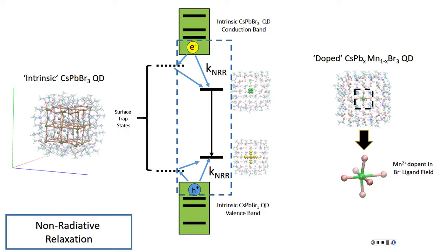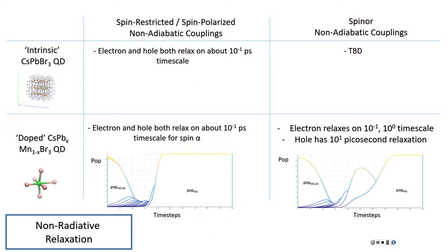So, non-radiative relaxation. The way that can be modeled is the perovskite is still going to be the absorber, so the excitation is going to be on the perovskite. It relaxes to the band edges of the perovskite, and then the electron and hole can relax to the dopant states inside the gap at some rate. Ideally you'd like them to be at the same rate, because otherwise you'll have a hole waiting for an electron, and where it could be emitting, it wouldn't. So ideally the rates to reach the manganese states are the same.